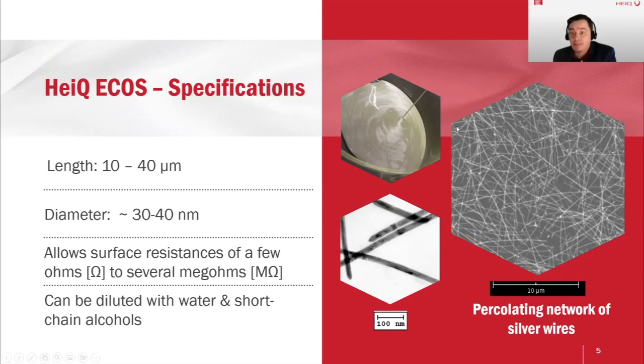And these tiny white structures that you can see here are the silver wires. And if you take any point on this surface, you can see that we form an interconnected network among the entire surface. And this interconnected network is responsible for conductivity. And the areas that appear gray or black here in the SEM, in the scanning electron microscope, are transparent to the human eye, at least if you use a transparent substrate. Therefore, with silver wires, with HeiQ ECOS, we can generate transparent and conductive surfaces.